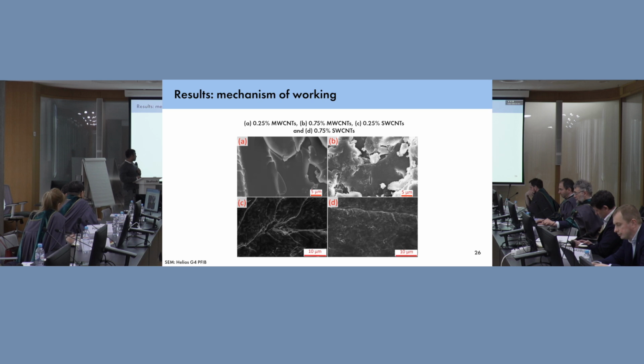For our single-wall carbon nanotubes, our structure is a bit different. They seem to be more flexible. The bundles are a bit longer in length, and the structure is not circular as we see with our multi-wall carbon nanotube composites. At the higher weight percentage, very well-formed percolation network, good amount of connections over here, which gives us our higher electrical property and lower tensile piezoresistive response.